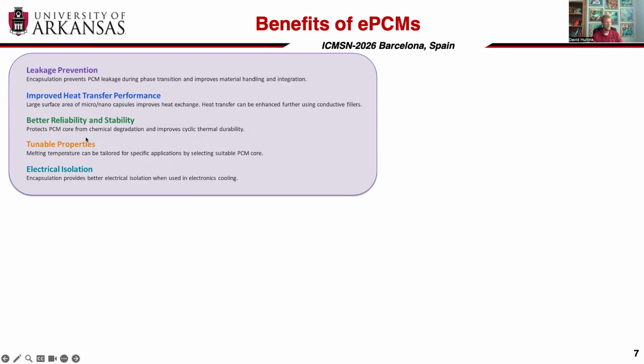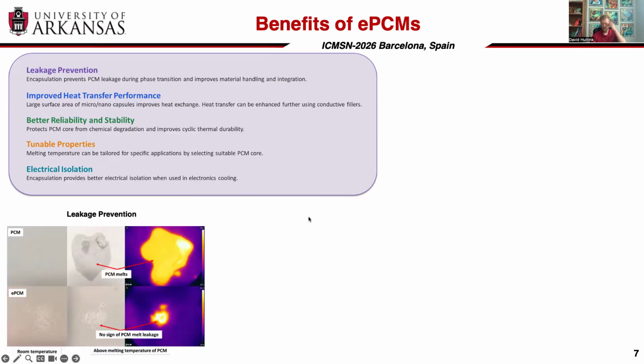And moreover, we can improve the reliability and stability of the PCMs, and our synthesis process allows us to tune properties with the different materials that we use. And the choice of materials also can help with electrical isolation and incorporation to other materials. So just a quick note on the leakage prevention. When you have a normal PCM or bulk PCM like paraffin, for instance, as you heat it above the melting point, it melts and it flows and it spreads out, which has to be dealt with.